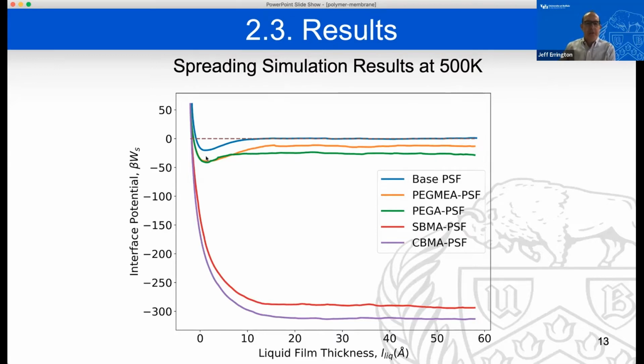Okay, so here are the different interface potentials, and what are these telling us? Well, if we look at just the base surface, you have an interface potential that has one of these global minimums, turns into a plateau. So that's telling you that the base surface, as well as the two systems, the orange color here and the green color, both of those are for the polymer tethers that are non-zwitterionic in nature. So all three of those systems have this minimum in the interface potential followed by a plateau region. So the qualitative conclusion that we come to is that all three of those systems would end up being in the partial wetting regime. In other words, if you put a fluid onto that surface, the liquid water would bead up into a droplet.